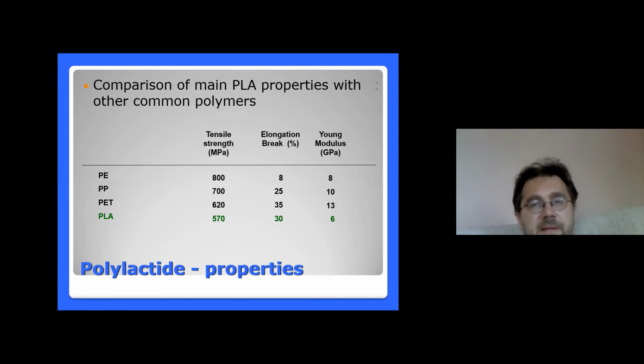Okay. And I would like now to compare the mechanical properties of polylactide fibers with other popular polymers like polyethylene, polypropylene, or polyethylene terephthalate. Let's look at the tensile strength. You can see that we have 570 for polylactide, so a little lower than polyethylene terephthalate, but this difference is not very big. So all of this depends on the final application. Elongation rate about 30%, so between polypropylene and polyethylene terephthalate. And Young's modulus is about 6 gigapascals, so not far from polyethylene.